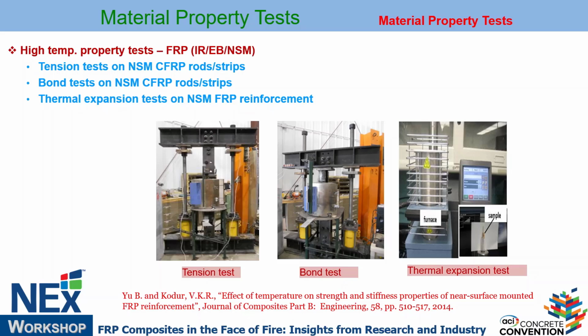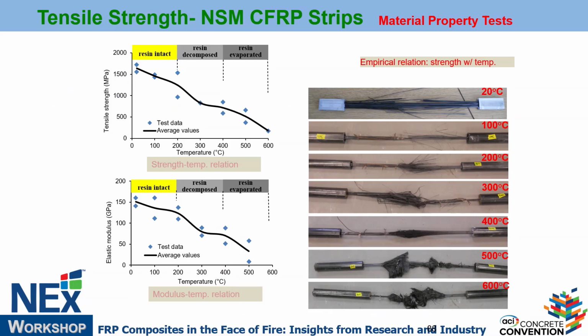It's much more complicated because the grip during the bond test, each thing is a PhD thesis. For example, my students have worked on bond strength. They have to develop a new test method to address different FRPs, how to get the grip on these materials, right? So, we did many of these tests, both thermal properties and mechanical properties. Just to show you quickly the results, this is for NSM type of CFRP strips. This is tensile strength versus temperature in degrees centigrade.